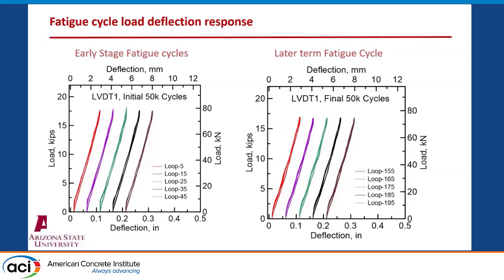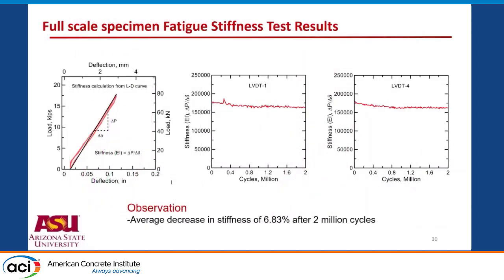For simplicity of showing the results, we're only looking at the head and the tail end of the test results. Each one of these curves represents 100 cycles in that time domain. From that, we calculate the stiffness of the sample, and here we plot the stiffness as a function of the cycles gone through. Technically, we see that there is some stiffness loss as the sample is exercised, and so there is some damage. But the average decrease in stiffness of the section post-cracking is about 7%.